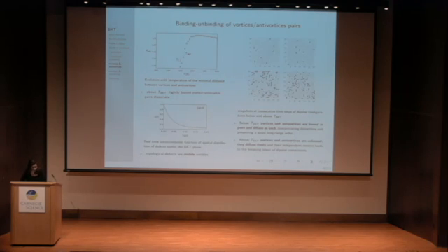Yes, so the picture is rather small, but if you look here, for instance, in this region, you see that the dipoles are rather correlated, but on length scales that are not that of full order. I mean, the correlation is not constant throughout space. But there are small regions where the dipole configuration features an extended correlation. So it's a power law. It means that the correlation drops less fast than in the exponential behavior characteristic of a disordered system. So we are in between a state of real order and no order.